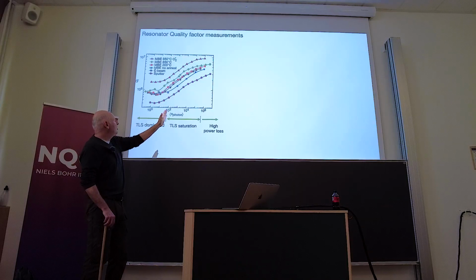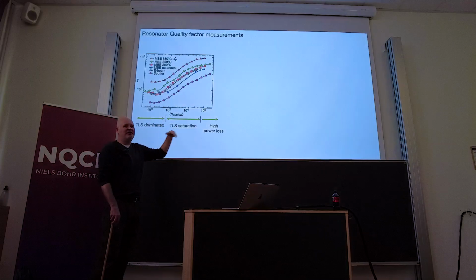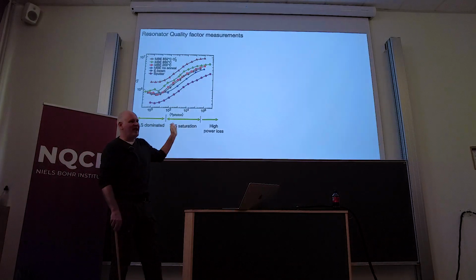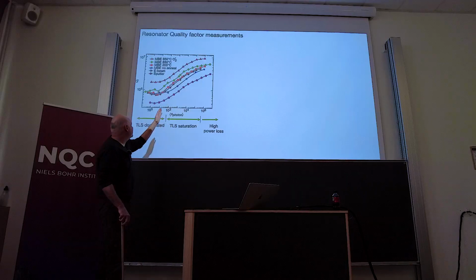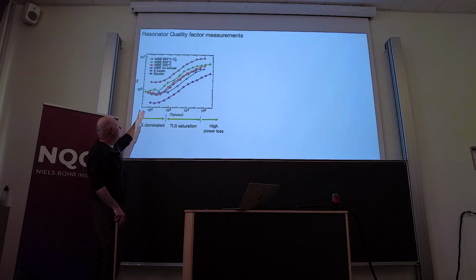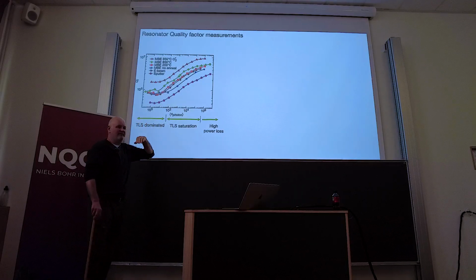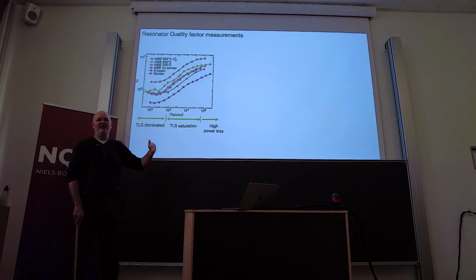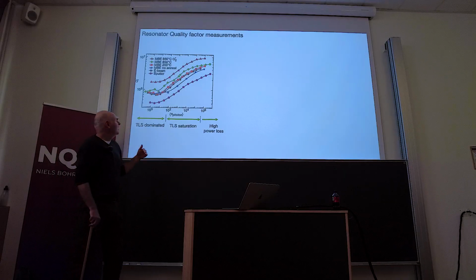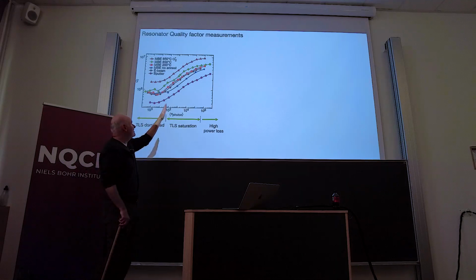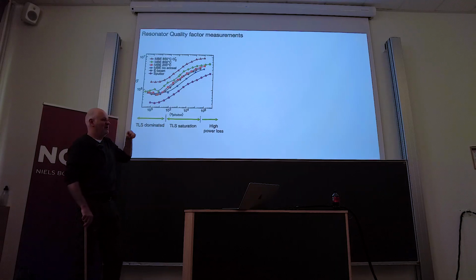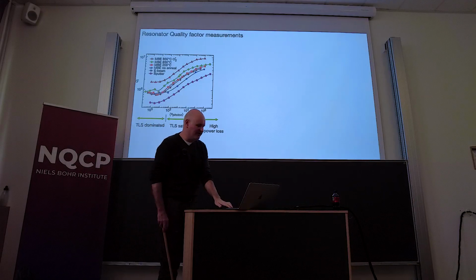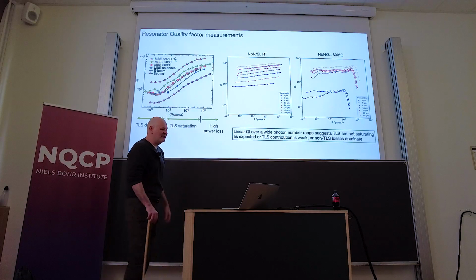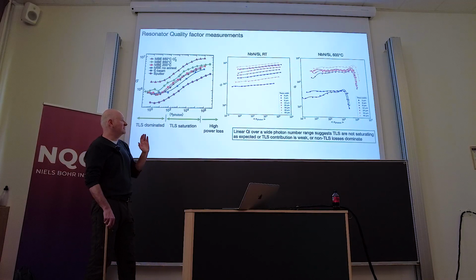As you go to lower and lower power, essentially what happens is at higher power, you saturate defects and loss channels, and the quality factor increases. As you get down to the single photon level, you reach a point where the loss channels are no longer saturated and the quality factor decreases. And so this is what you expect. And this shape actually correlates with the concentration and type of loss channels that you have in your chip, in your device. The reason I threw that up was because we don't see that.